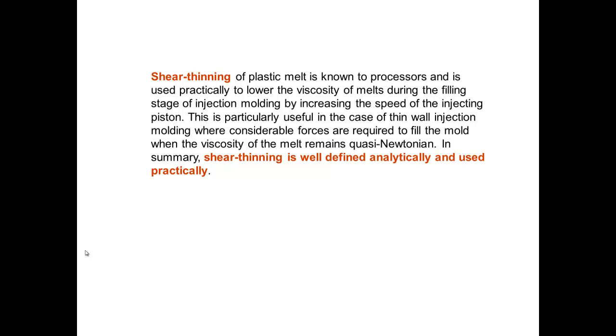Shear thinning of plastic melts is of course known to processors and is used practically to lower the viscosity of melts during the filling stage of injection mold by increasing the speed of injection piston. This is particularly useful in the case of thin wall injection moldings, for instance in micro moldings, when you have extremely small parts to make, where considerable forces are required to fill the mold when the viscosity of the melt remains quasi-Newtonian. In summary, shear thinning is well defined analytically and used practically.